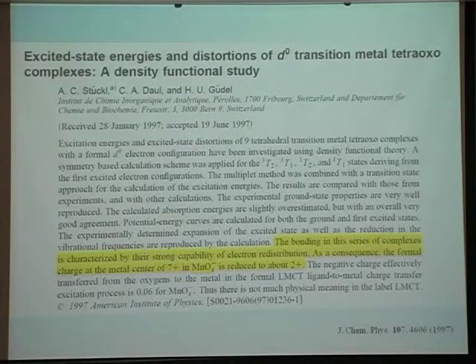How does that reduction happen? Of course, the reduction happens because oxygen gives out lots of electrons to the manganese. Manganese gets reduced, and these oxygens have lots of holes in them. There is a huge covalency because of this, and that's precisely the reason why the manganese-oxygen bond lengths become so small.